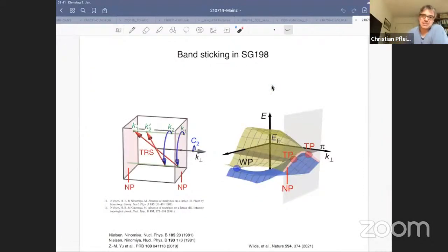Okay, now there's one thing missing in these considerations, and that is something that's been in the literature actually also for quite a long time. And I think I'm missing to cite some of the important papers here, so I apologize. This cobalt silicon belongs to a space group, which is space group 198. And as I mentioned in the beginning, the combination of this screw rotation, this non-symmorphic crystal structure, with time reversal symmetry basically means that you connect basically by these